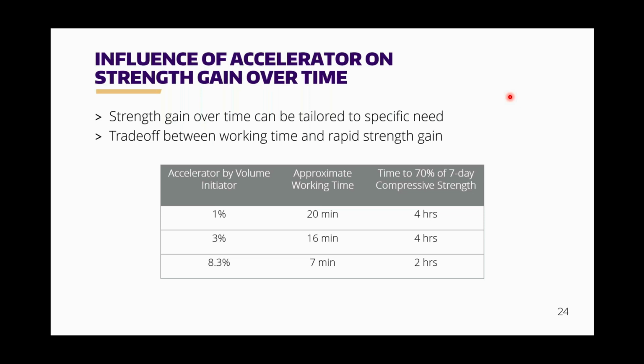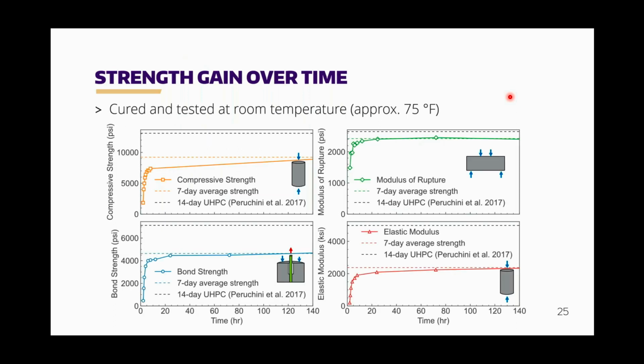So really you're trading off your working time with your strength gain, and that can be tailored depending on what your conditions are at the time of casting or pouring. For our tests, we used 3%, so around 15 minutes of working time, and like you'll see coming up, about 4 hours to reach that 70% marker. Looking at the strength gain over time, diving a little bit more into it, for all of these specimens, we cured and tested them at room temperature, so about 70-75 degrees Fahrenheit.